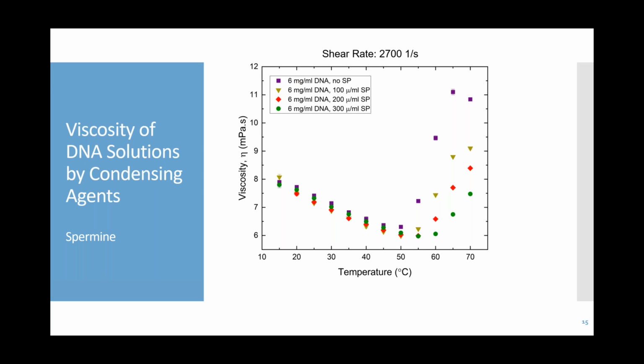Now let's see what happens when we start increasing temperature. As you know, in DNA structure, two single strands are bonded into one double helix, and initially the increase in temperature disrupts hydrogen bonding that leads to partial separation of double strands. So you're going to have more expanded structure, and there would be some potential crosslinks with single strands and neighbors that lead to an increase in viscosity. So this viscosity increase that you see in this plot most likely occurs because of DNA melting.